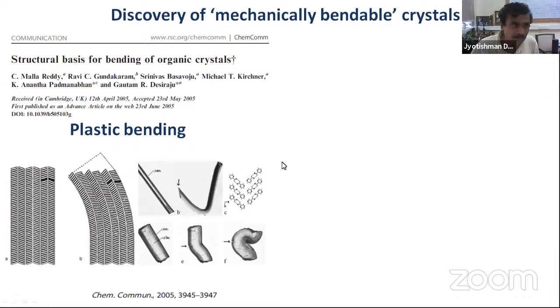And when you have polycrystalline samples, those facets are not in the right orientation for the entirety of the beam to go through, and you get very clean spots. Now, yes, that also was a length scale argument, right? Yes, so the probing beam and the length scale of the entire crystal should both be important. And since you bend it out, if I probe it at the bent region, would I see a diffraction pattern which is reminiscent of a single crystal, or would I see a diffraction pattern composed of multiple polycrystalline parts? Yes. So let me make one thing clear.